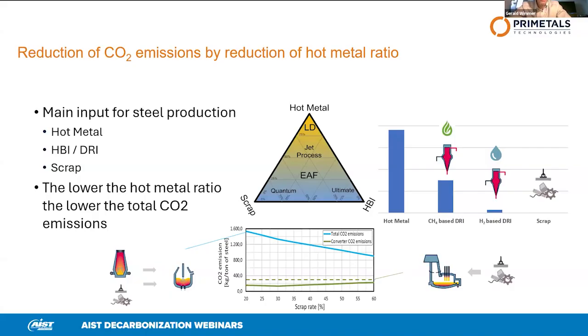So here we have shown the CO2 emission of the route, blast furnace and BOF converter, total CO2 emissions as a function of the scrap rate. And we see, of course, that the emissions of the converter shown in green do not change, but the overall emission changes: for about 1% of scrap rate increase, we get roughly a reduction of CO2 emissions by 1%. This will not lead us to carbon neutrality because the scrap rate in BOF converter steelmaking still is limited. But this is a nice, simple way, as a first step, to get to lower CO2 emissions by increasing the scrap rate by some 5 to 10%.